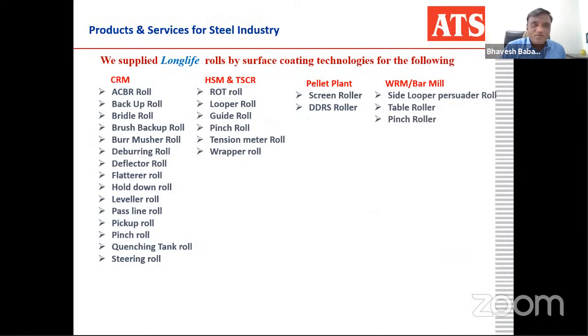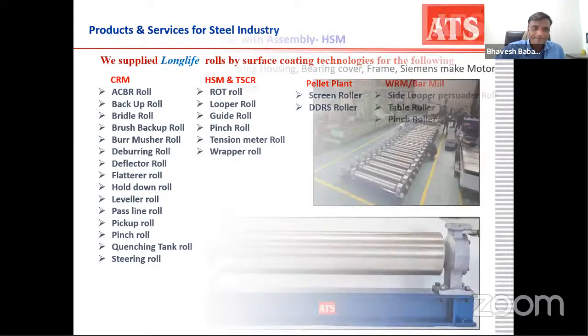We are producing rolls for CRM lines, HSM lines, pellet plants, and WRM in the bar mill. Generally, in the CRM lines, we are producing rolls like ACBR, backup rolls, bridle rolls, meaning all the process rolls with special coatings like hard chrome plating, ceramic coating, and tungsten carbide coatings. So all types of rolls we fabricate at our Ahmedabad job shop. We manufacture rolls from 50 mm up to 1.5 meter diameter at our Ahmedabad plant.